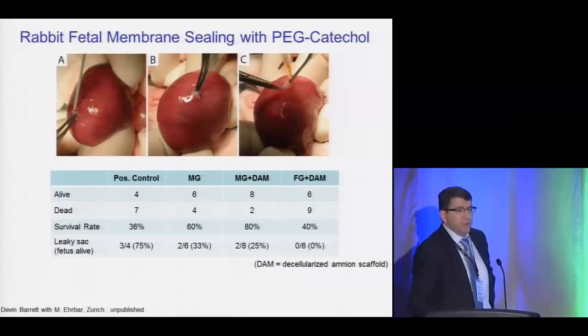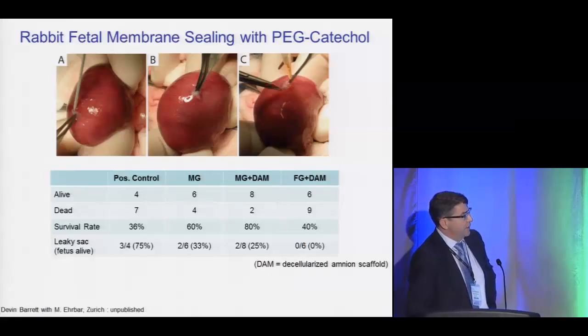We're currently at this stage here with a rabbit fetal study. This is actually an interesting study. It's given us some glimpses of hope that this could be a very useful biomaterial. If you expose the fetal membranes and poke the hole but do nothing to fill it, you get a survival rate of about 36%. If you fill it with our mussel glue, the survival rate rises to 60%. If you use the mussel glue plus decellularized amnion, we get about 80% survival. And fibrin glue plus the decellularized tissue remains fairly low. So we're pretty hopeful about the outcome of this, and are planning sheep in vivo studies later this year.